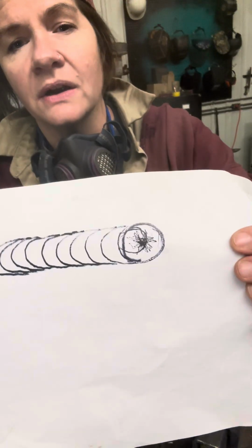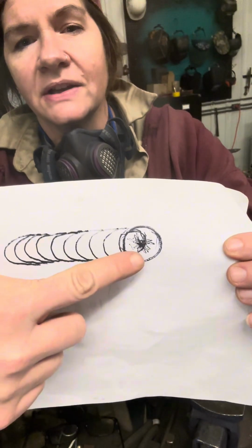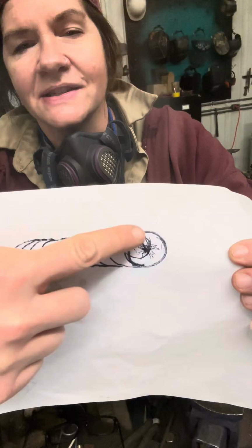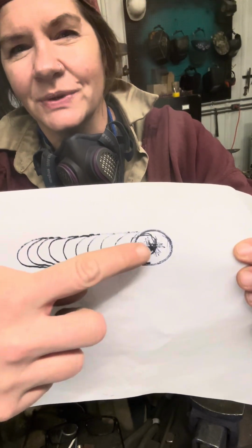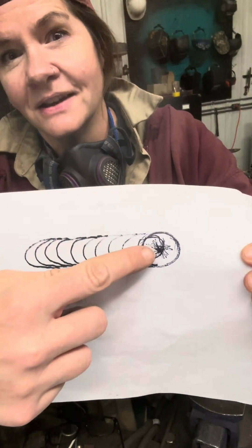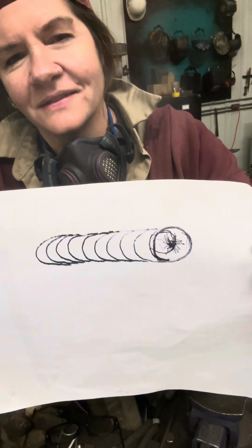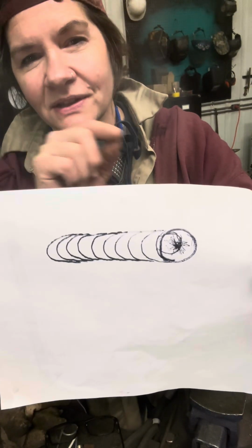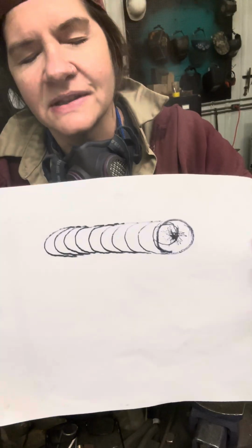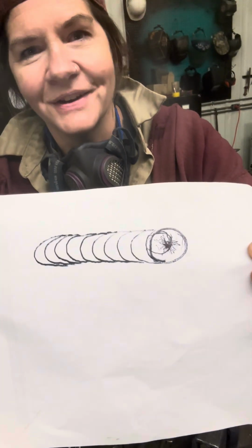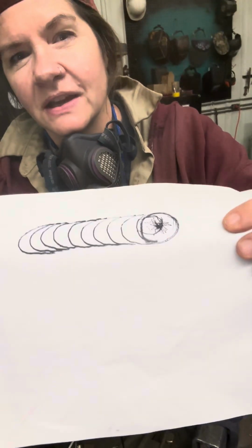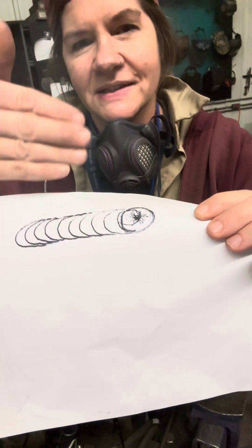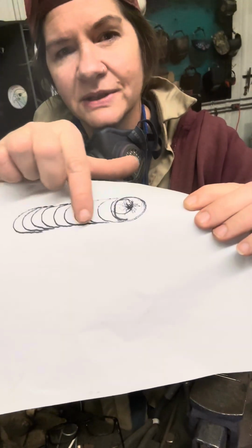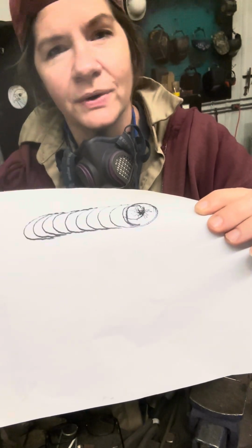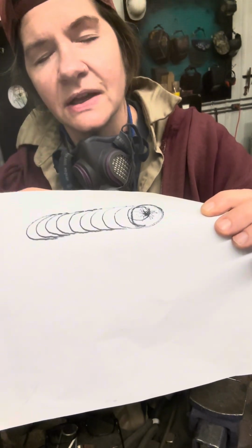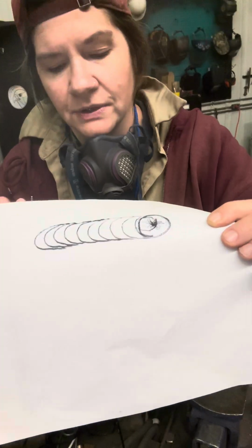And that is where the molten material is trying to cool, but is pulling against the outside that's already solidified. And since it's still liquid, it pulls apart from itself, and it leaves a perfect little hole there. And it does sometimes have those whiskers, the little cracks coming out from around it, and that's where it gets the name star crater. And they aren't just on the surface, they can go deep into the weld. If you were to cut that in cross section, it'll go all the way through the weld material you just laid down, whatever rod you've burned off, whatever filler material you've added. And sometimes in severe cases, it can propagate through the base metal.